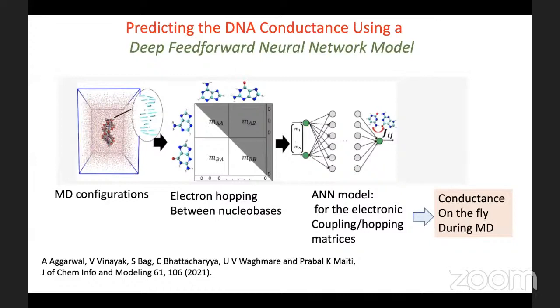So the first project is where I want to communicate to you. This is an example where we looked at properties of fairly complicated extended molecular materials, such as the DNA molecule, and predicting its electrical conductance using molecular dynamics. But it's impossible to do quantum mechanical calculations for fairly large molecules. So what we do in this approach is we pick a configuration from molecular dynamics, and the hopping or electron coupling between different base pairs, which is shown here in terms of a matrix. Those coupling elements are modeled using artificial neural networks. Particularly, we use a deep feed-forward neural network model. And then this can be used on the fly during molecular dynamics to predict electrical conductance of this fairly complex molecular system. Okay, so I will be happy to bring in artificial intelligence or machine learning ideas into modeling some of these materials we have.